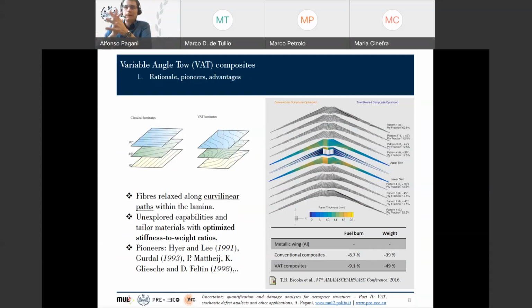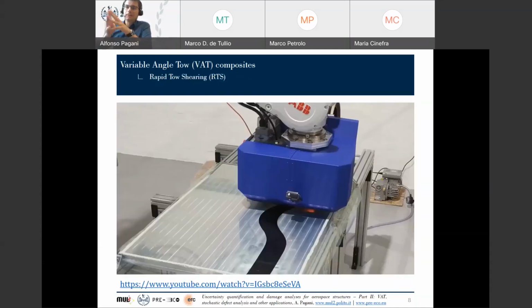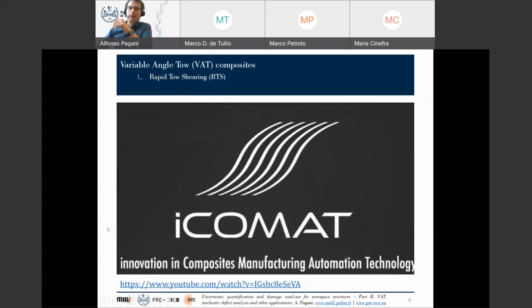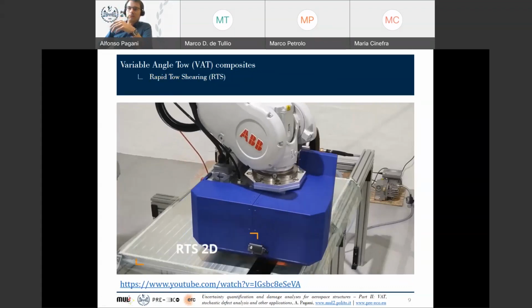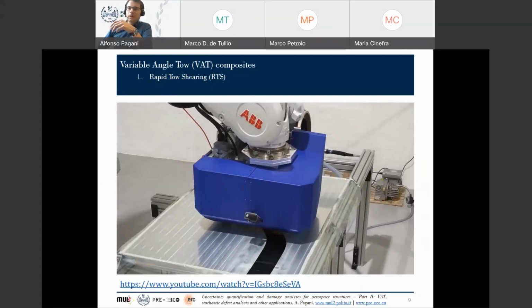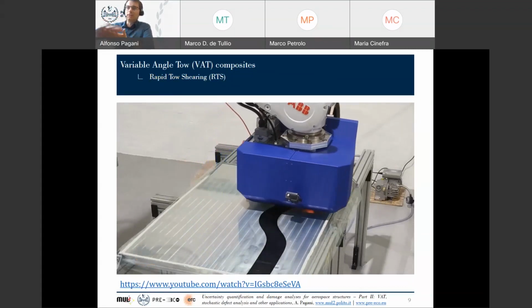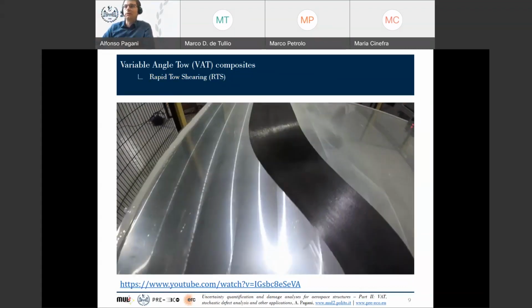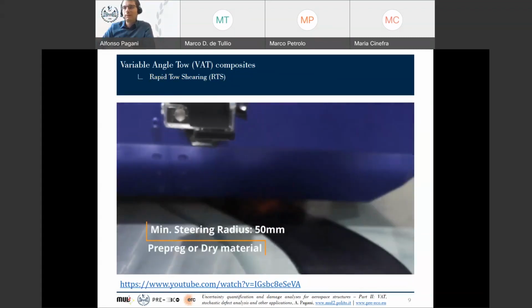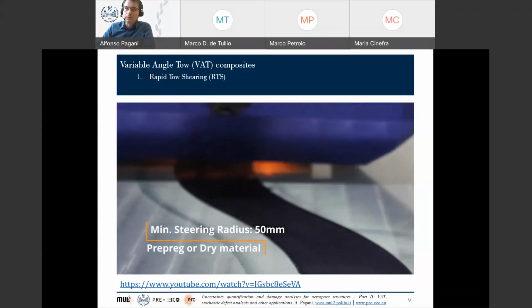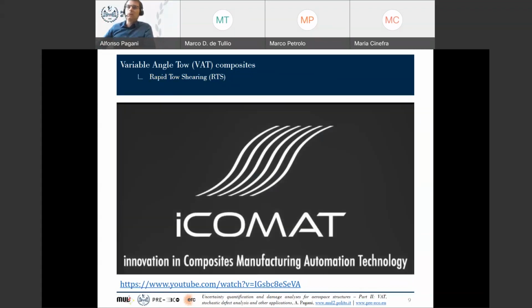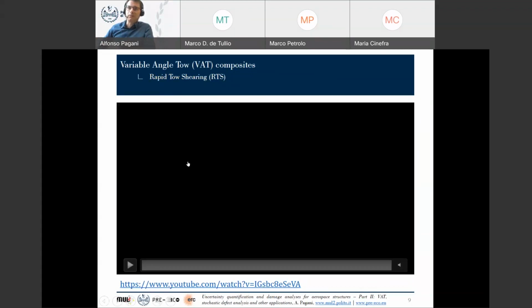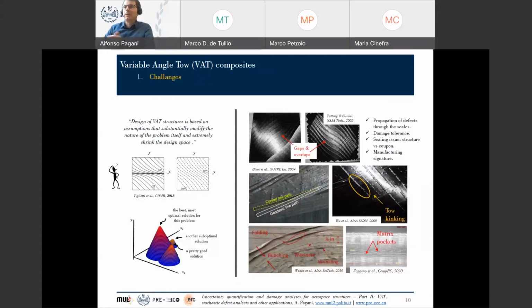But there is a drawback. Of course, now we can build these composites. This is, for example, a very new technology, rapid tow shearing, developed at University of Bristol, and they're continuing to study this process, in which you can essentially steer your carbon fibers along curves. And this is one of the best processes to develop this kind of structure. Anyway, if you use rapid tow shearing, automatic fiber placement, or ATL, still you will be facing defects.